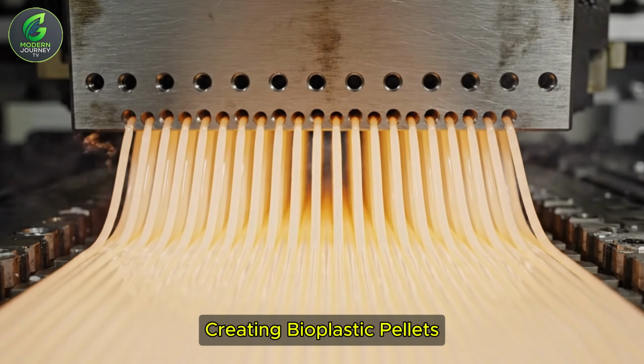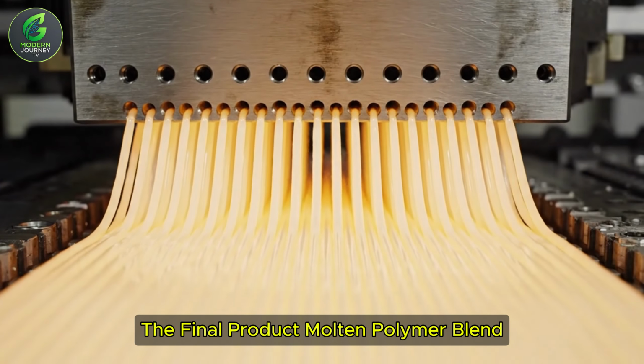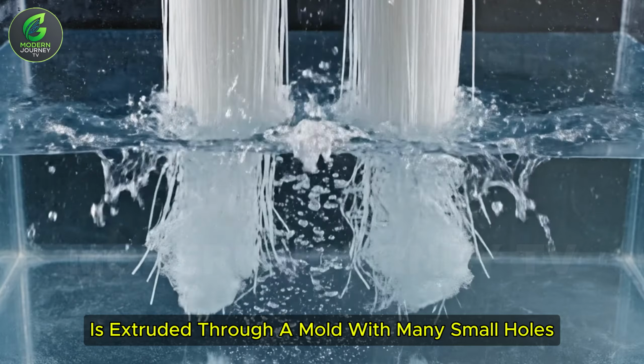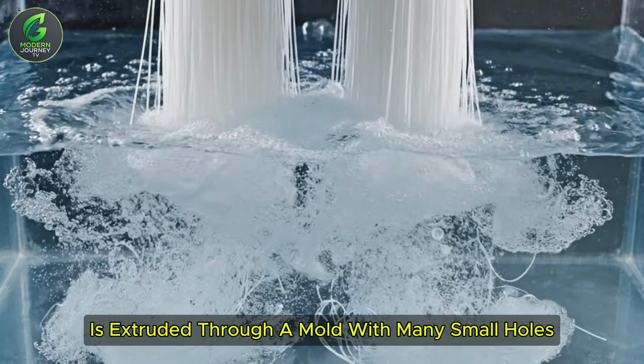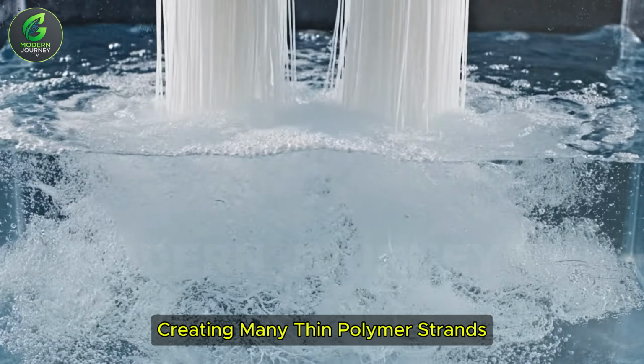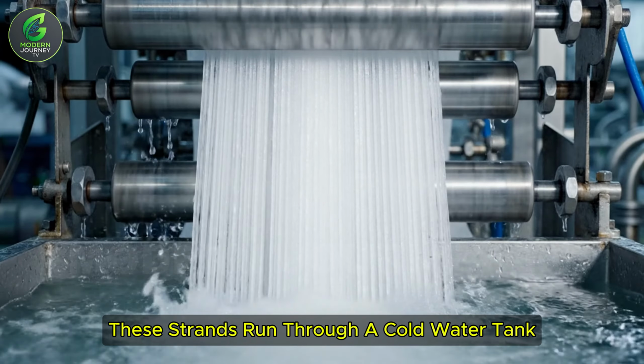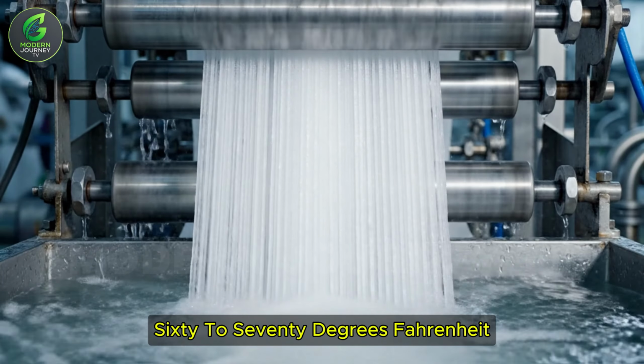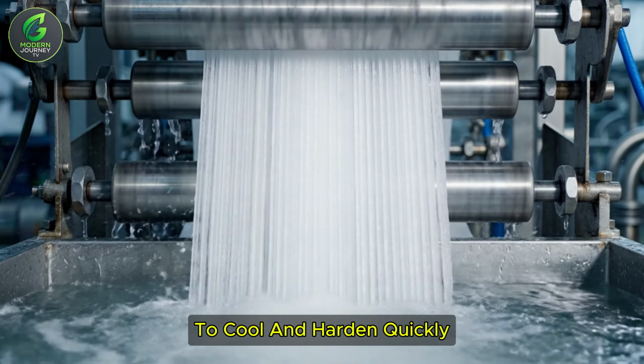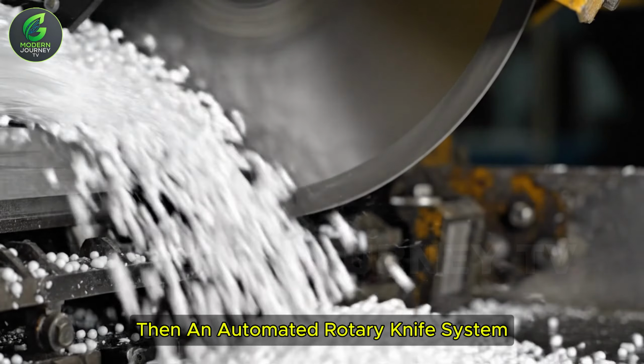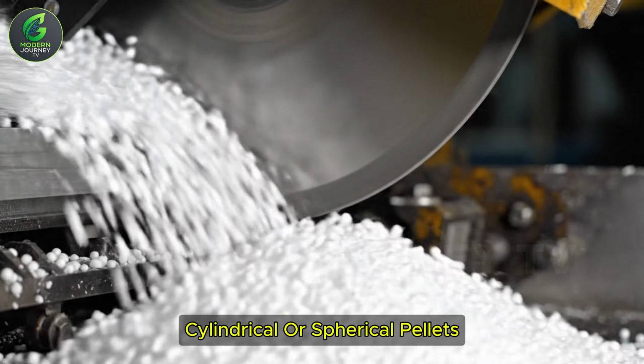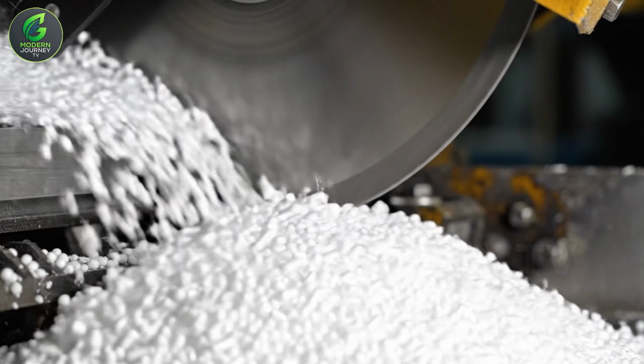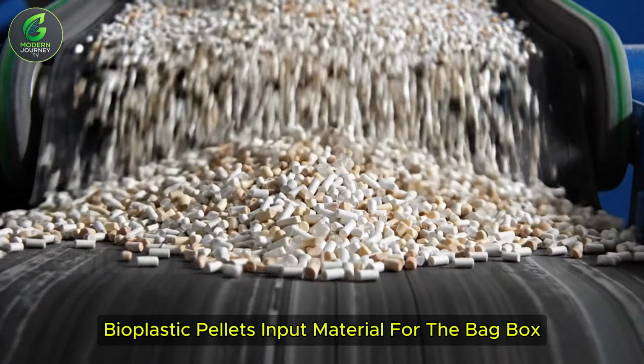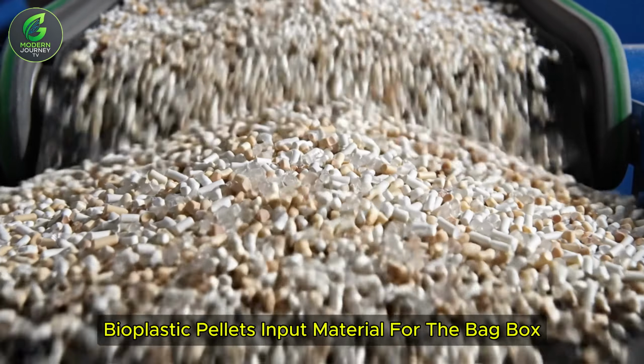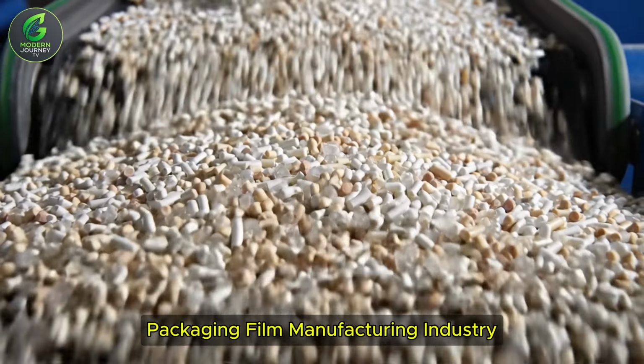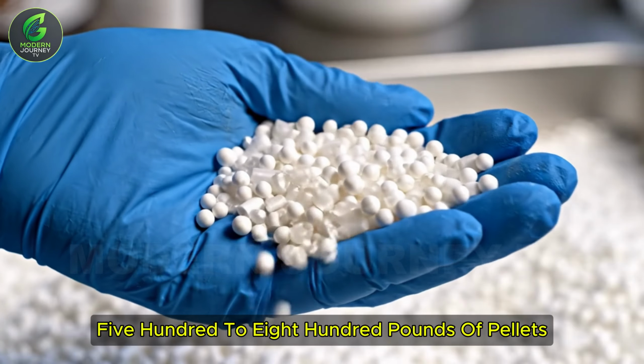Creating bioplastic pellets. The final product. Molten polymer blend is extruded through a mold with many small holes, creating many thin polymer strands. These strands run through a cold water tank, 60 to 70 degrees Fahrenheit, to cool and harden quickly. Then, an automated rotary knife system cuts strands into small cylindrical or spherical pellets, size 2 to 4 millimeters. These are bioplastic pellets, input material for the bag, box, and packaging film manufacturing industry, each hour producing 500 to 800 pounds of pellets.